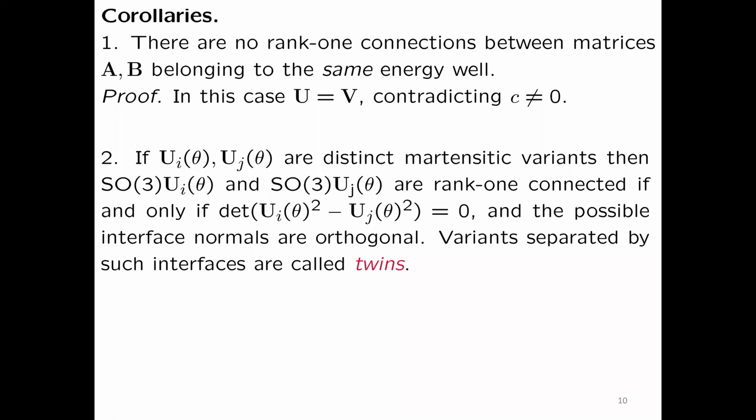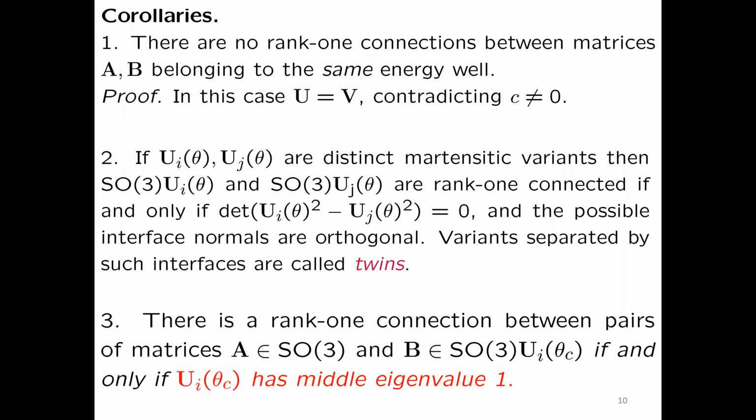And the variants separated by such interfaces are typically called twins. Now, here's a very interesting remark. So suppose we take A in SO(3). So that corresponds to the high temperature phase.